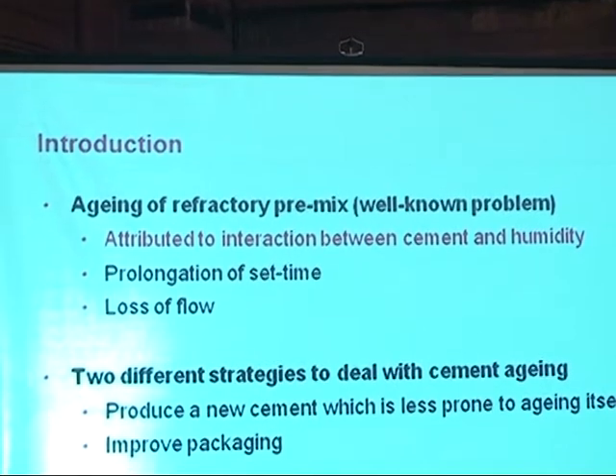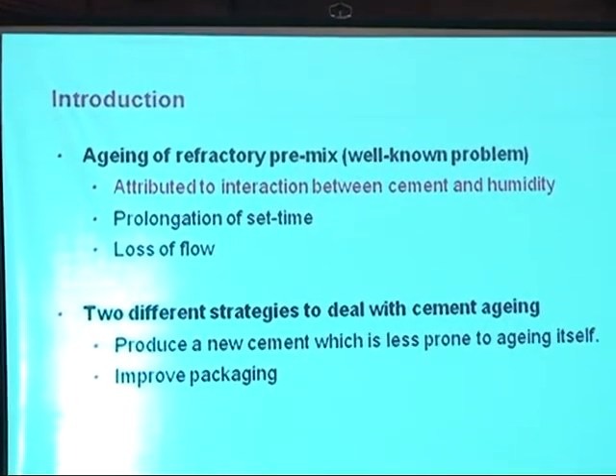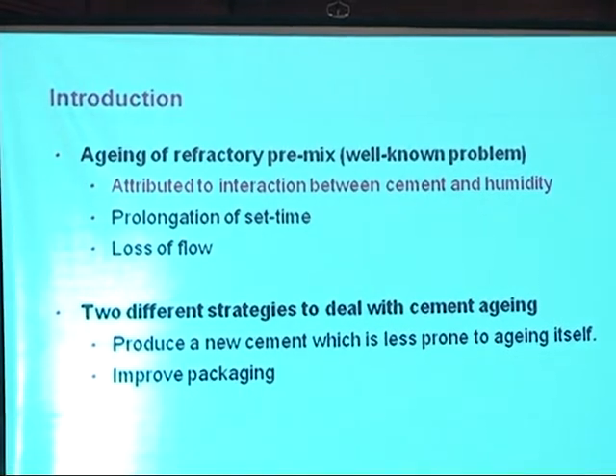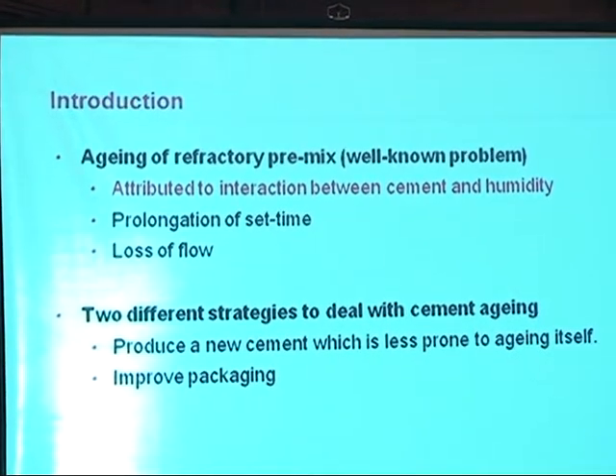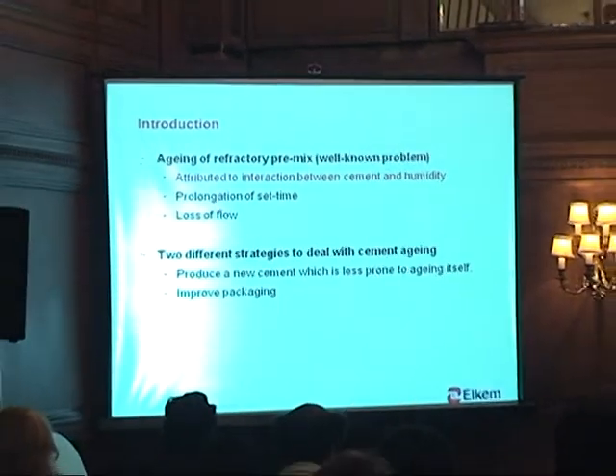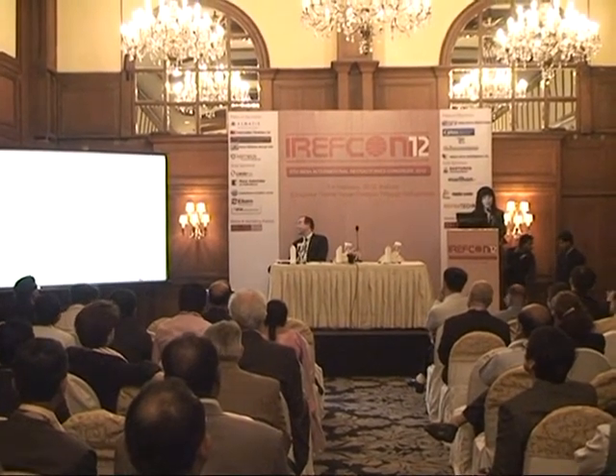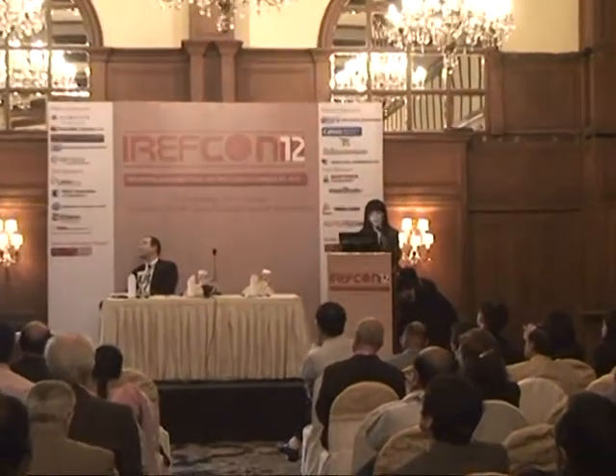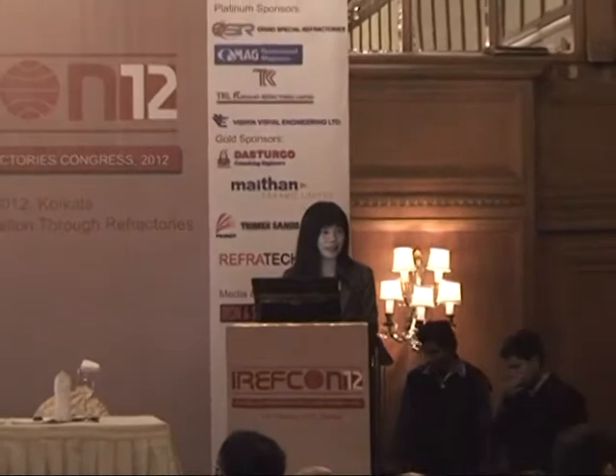In order to solve this problem, there are two different strategies that have been developed to deal with cement aging. One is to produce a new cement which is less prone to aging itself, or to improve packing by using plastic packing or vacuum packing or drums, or use both. The objective of this paper is to investigate the aging mechanisms and also try to find potential solutions to improve the shelf life.